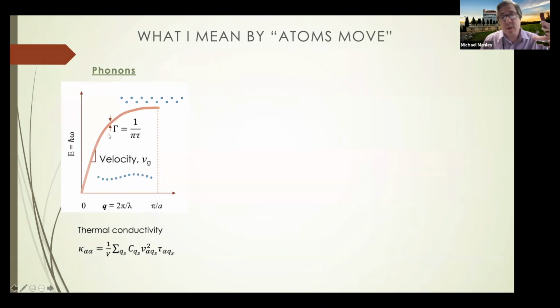There's another thing that you have to appreciate here, a couple of things. The slope of this line is the velocity. So that's basically how quickly energy is moving through the vibrations in the crystal. So that's an important parameter. Another parameter is that if phonons lived forever, if the vibrations lasted forever, this curve would be sharp. But it's not sharp because the vibrations scatter from things, from defects, from other vibrations, and so on. And what happens is that causes this to broaden out. But when we do a measurement, if we can measure that width, that's inversely proportional to lifetime. And that's another factor that comes in.